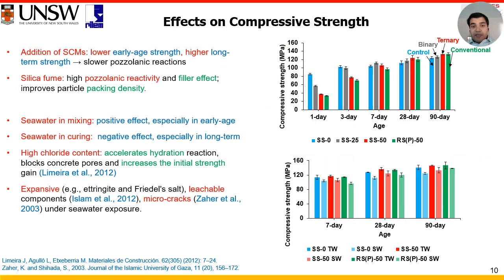Now the effects on the compressive strength. We have found that addition of SCMs can significantly lower the early age strength up to 3 days. However, after 28 days and beyond, the long-term strength will surpass the control strength. This is primarily because of the high pozzolanic reactivity nature of silica fume and its filler effect, which will improve the particle packing density.